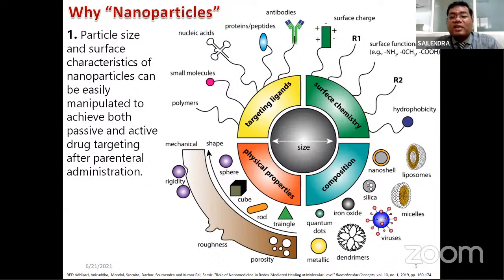Next is surface charge. Due to the charge present on the nanoparticle, it can remain in suspension or it can aggregate in suspension. If we know the zeta potential of a particle, if there is too much negative charge on the particle and two such particles are close to each other, there will always be repulsion among them. But if one particle has a positive charge and another has a negative charge, there will be attraction between the particles and that may result in aggregation.